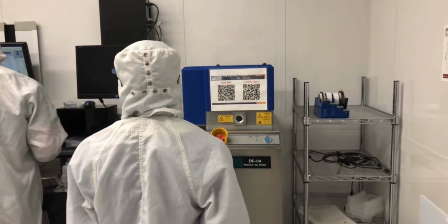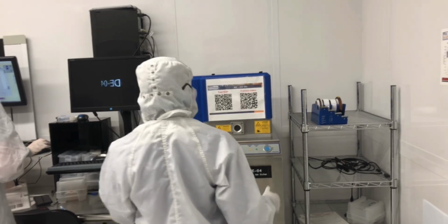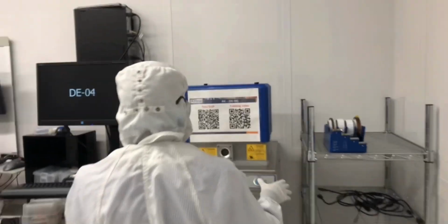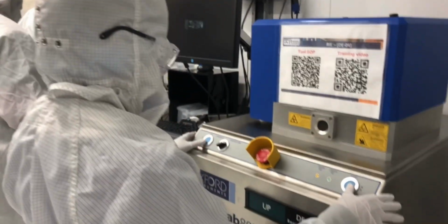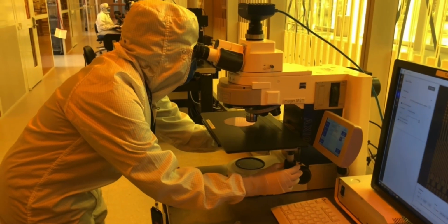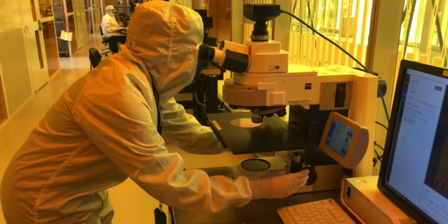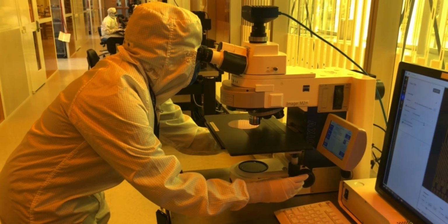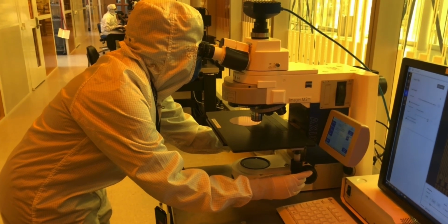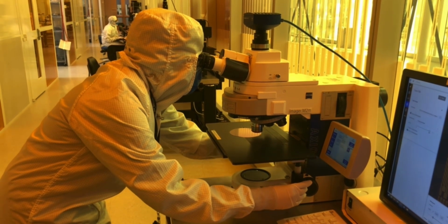Next, we travel to a different room in search of the Oxford 80+ reactive ion etch tool. The RIE removes the silicon oxide and silicon nitride that are not protected by a layer of resist. From here, we make our way back to the Drndić lab, where earlier we prepared a 40% potassium hydroxide solution to anisotropically etch the silicon layer.